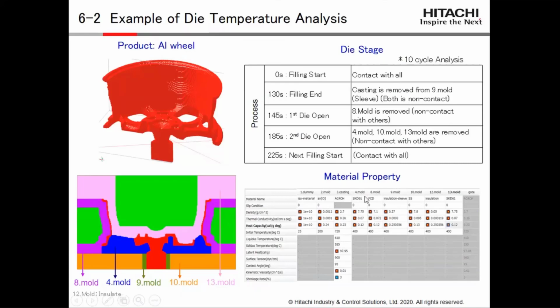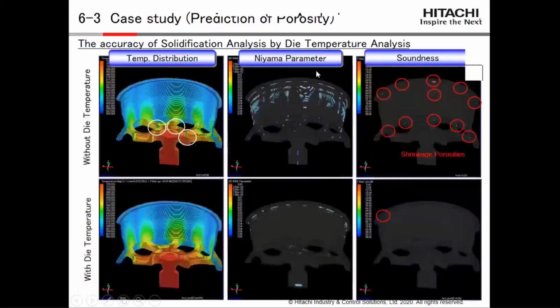So it shows an example of material property, the casting mold property. It shows temperature distribution, Niyama parameter, soundness and the possibility of shrinkage porosity. Without reflecting the temperature, shrinkage was happening in many areas.